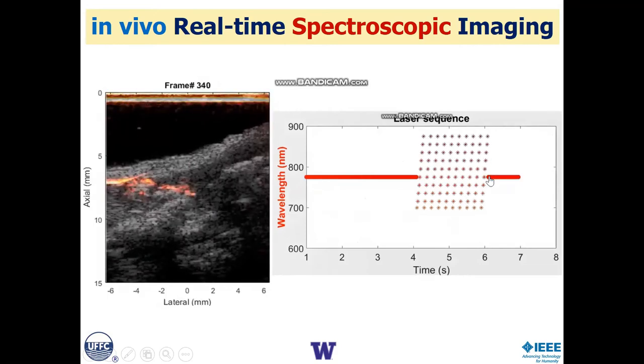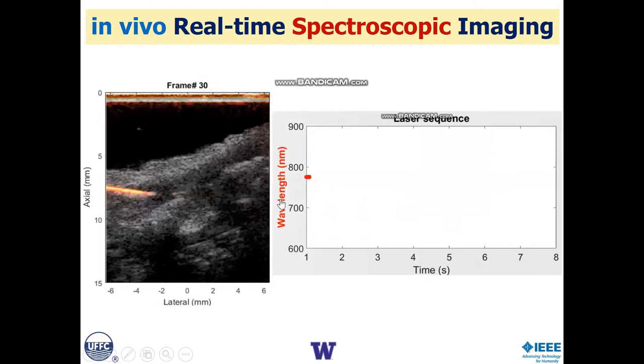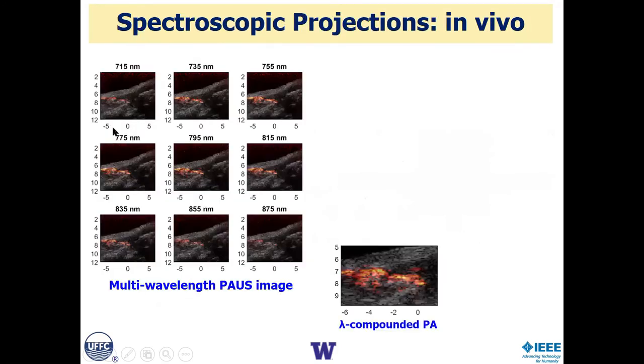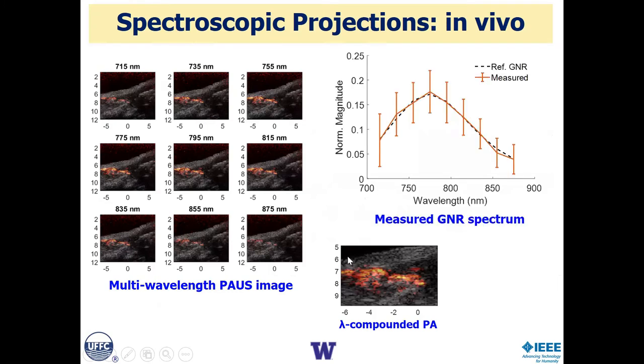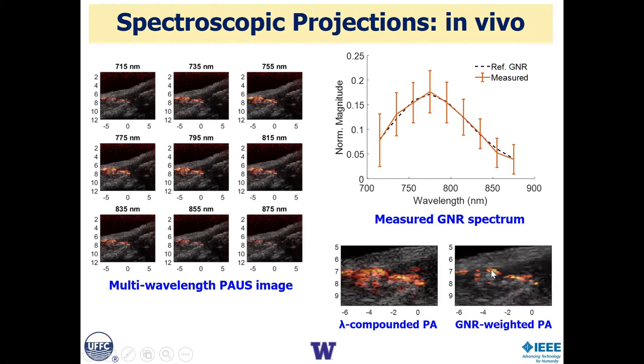Okay, and then finally, we do this in vivo in an animal model. Again, sweeping through these wavelengths rapidly, but here we have significant physiologic motion, and this just shows the motion correction. If I make these images but do not spatially register them, the photoacoustic image corresponding to the contrast agent is blurred and tremendously corrupted. However, when we do the correction for motion, we now have almost a perfect projection onto the contrast agents, and so we get a clean image showing the primary sites where we have injected agent. True molecular imaging using very simple laser systems embedded within a real-time ultrasound.